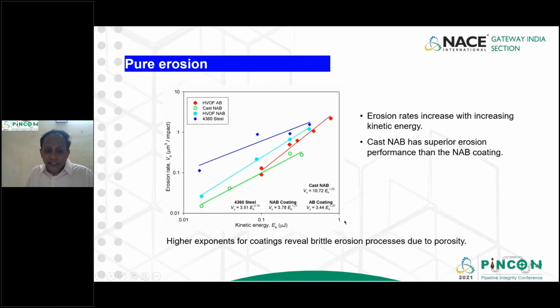Now these are the results, the volume loss per particle impact, which we call the erosion, and I looked into the kinetic energy. Kinetic energy is nothing but your velocity and the mass of the particle impinging on the surface. The similar behavior also, the cast NAB is here, the round one. You can see that the cast NAB at a very low kinetic energy also performs better. Erosion rate is less, but when you come to steel, it is very high. Similarly, the coating is also very low. This is what we have observed.